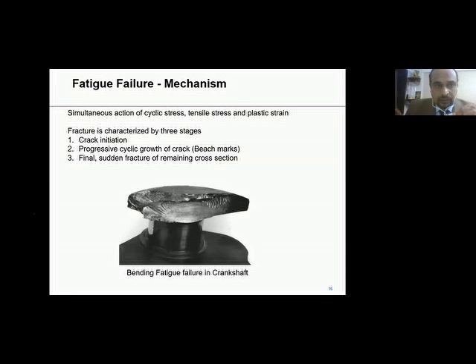So as you can see in this slide, the fatigue basically happens in 3 stages. The first is crack initiation, then progressive crack growth due to cyclic stresses, and then final sudden rupture of remaining cross section. So as you can see here in this crankshaft piece, the crack initiation happened through pin fillet, and then these are the beach marks, and the final rupture zone is seen here. So typically 3 stages of failure.